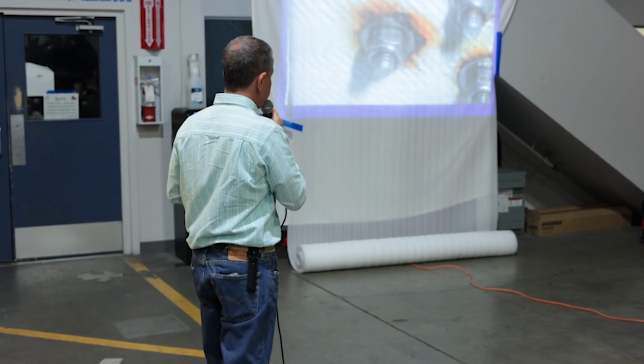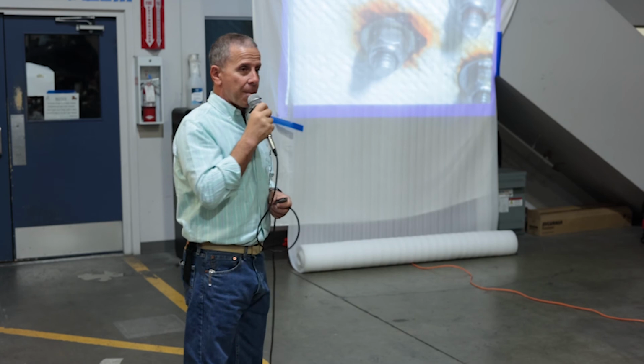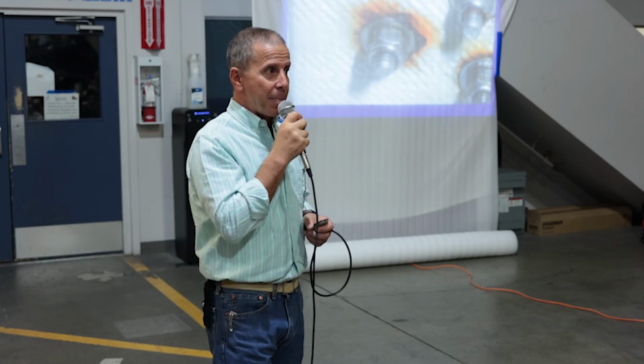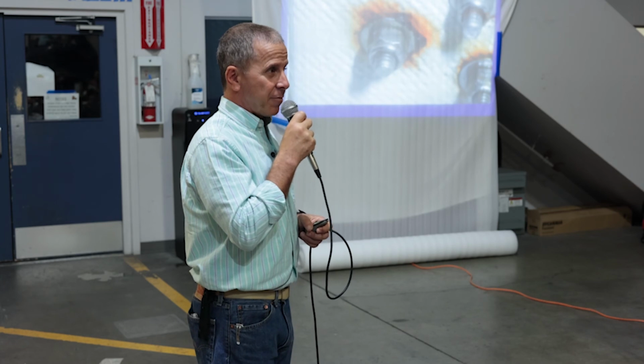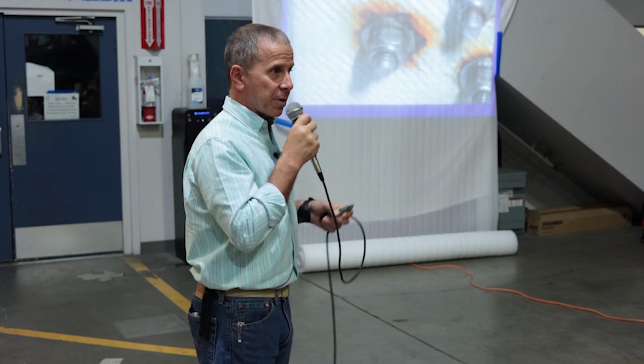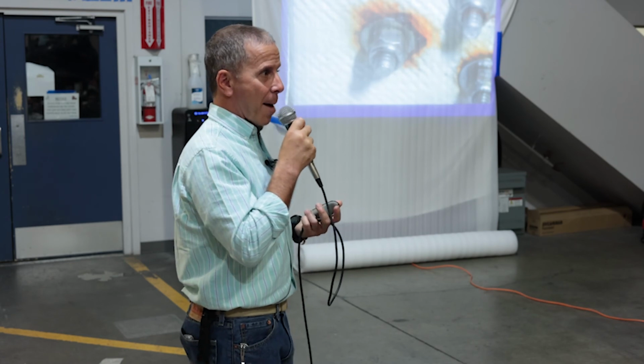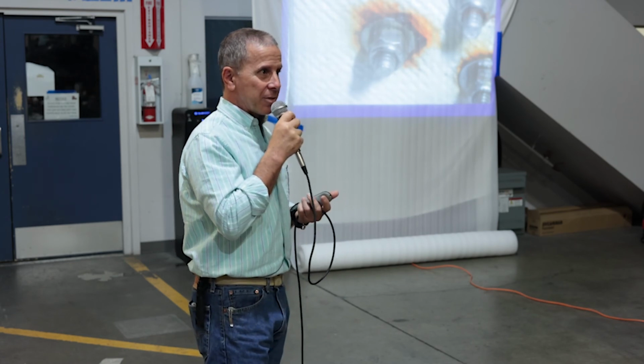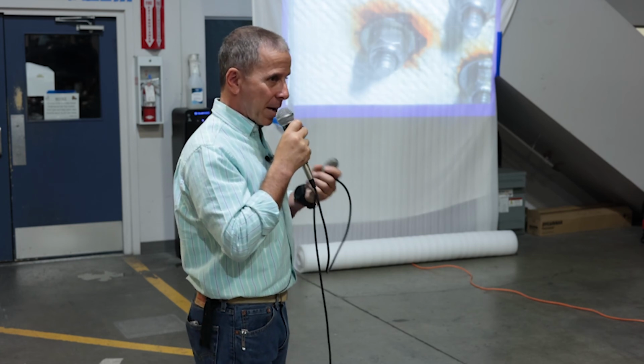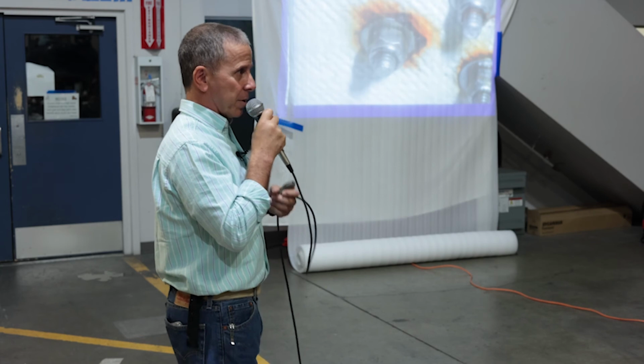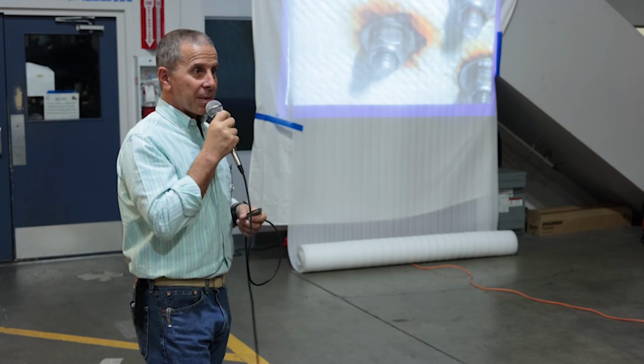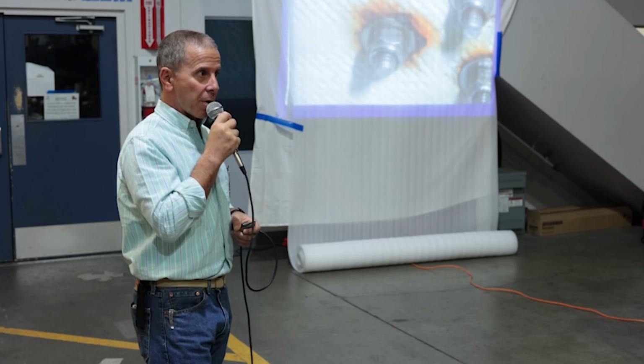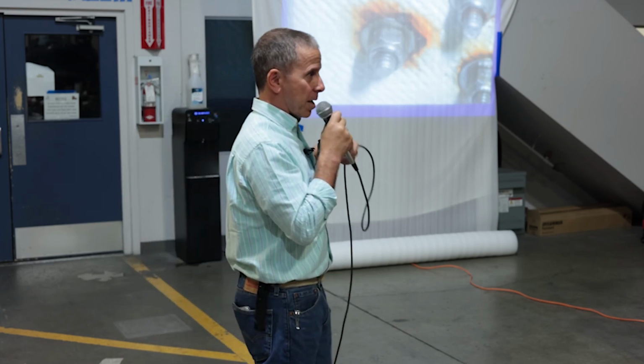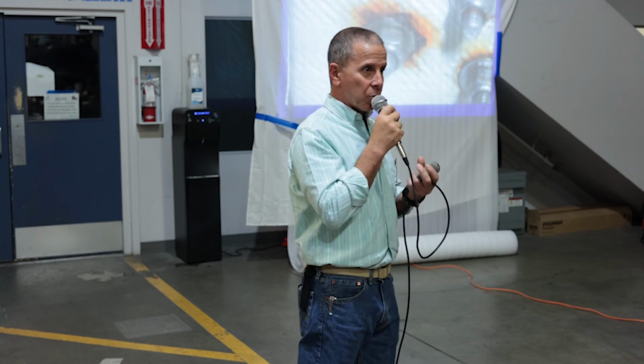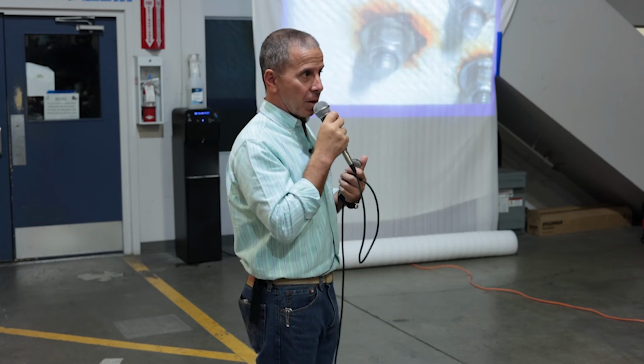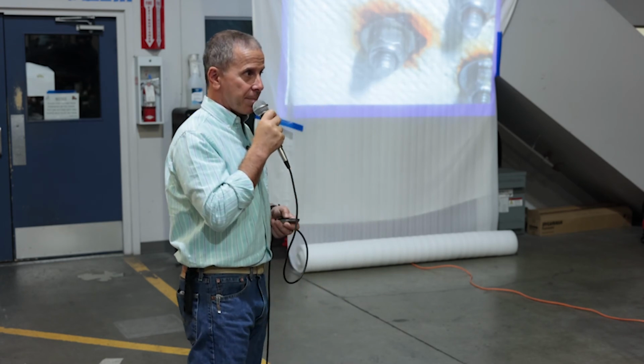Now, here, this is a good example of why it's not a great idea to bed the inside of a fastener. If you use sealant around the nut side, the part that's inside the boat, you're creating a trap for water to get stuck inside that void. So bedding or sealing the outside, whatever you're using, whether it's a polyurethane sealant or mastic, fine. We know we need to do that on the outside to keep the water out, but do not put anything on the inside because, again, that can create sort of a plug that will trap water in that void and lead to, or maybe exacerbate, a crevice corrosion type scenario.